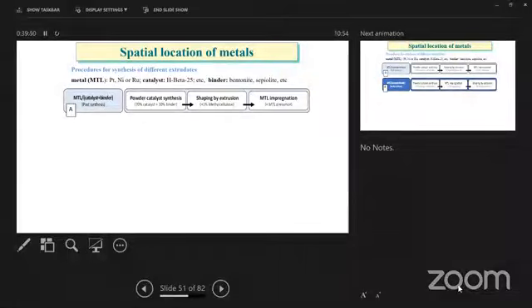So a few words then about the methodology. We use this procedure for different types of metals, for platinum, for nickel, or ruthenium, we can do it for iridium. And the zeolite can be whatsoever, ZSM-5, beta, MCM-41. And then the binder, bentonite, or sepiolite, or whatever. It doesn't matter that much. So the first idea is that